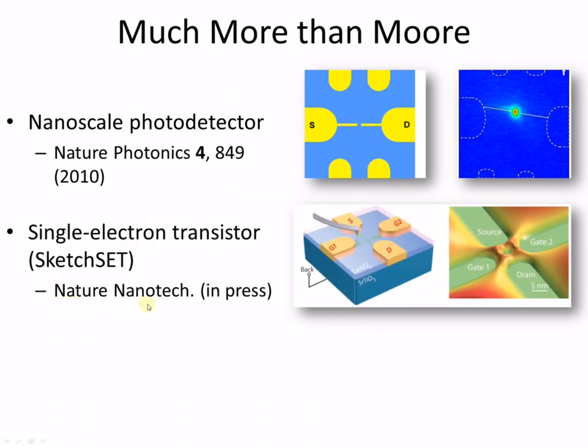Also, we have some work that is going to be published shortly. It was also discussed in a paper at the March meeting, where we created a single electron transistor, and it's incredibly simple to make these transistors. We simply write, in one instance, a cross, and then move to the center of the cross and apply an erase pulse, which creates a cylindrical barrier region. Then without moving the probe at all, a self-aligned positive voltage pulse is applied that creates the island. So this gives us an island with a source and drain and two side gates.